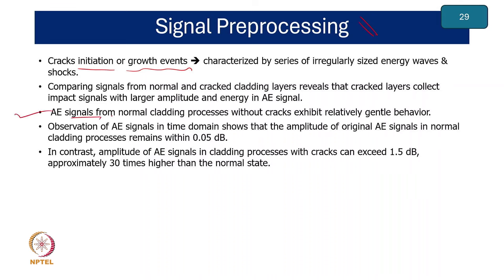A signal from a normal cladding process without a crack can exhibit different behavior. And what is that behavior? See, normal signals, whatever we are getting, will be lesser than 0.05, so there is some sort of limit. However, if a crack is there, the signal will increase significantly, maybe to the tune of 1.5 decibels. So it is almost 30 times higher. This is the common range.